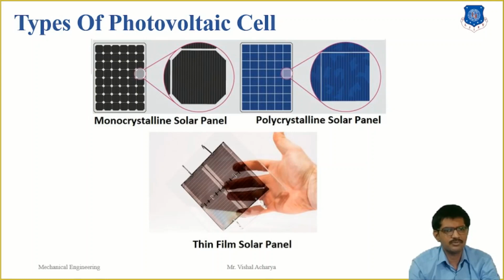much cheaper to produce. Their efficiency, however, is greatly reduced because the silicon atoms are much less ordered than in their crystalline form, leaving dangling bonds that combine with other elements, making them electrically inactive. These cells also suffer from a 20% drop in efficiency within the first few months of operation before stabilizing, and they are therefore sold with a power rating based on their degraded output.